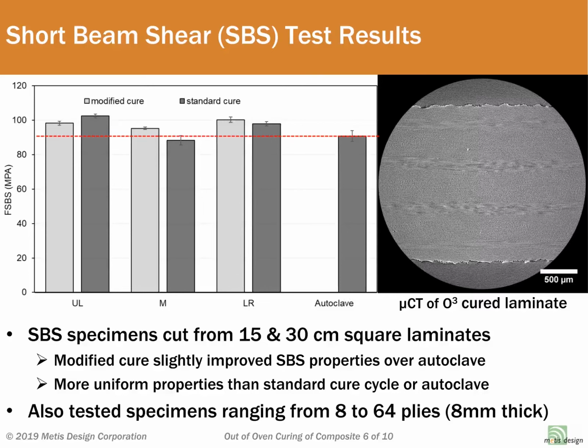During the course of this STTR, we have thus far fabricated composite laminates using this conductive out-of-oven approach, including our modified cure cycle of up to 60 by 60 centimeters and up to 8 millimeters thick. Our collaborators at MIT have thoroughly characterized these laminates, including degree of cure via DSC, void content via micro-CT and SEM, and strength via hundreds of short beam shear tests.